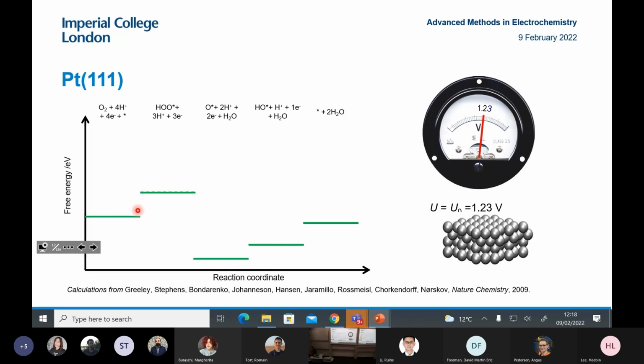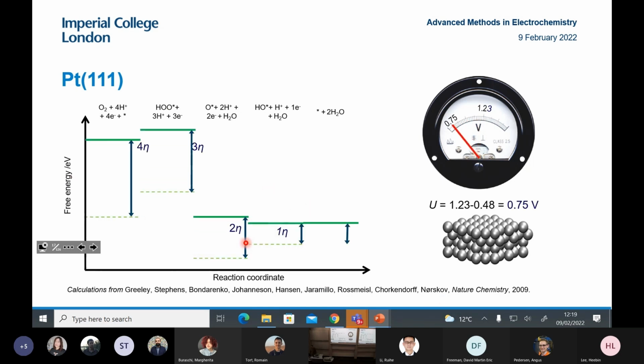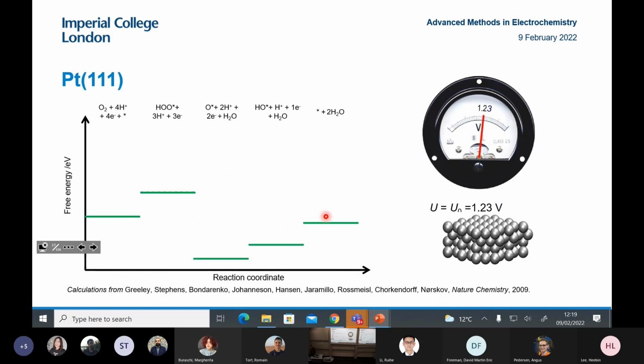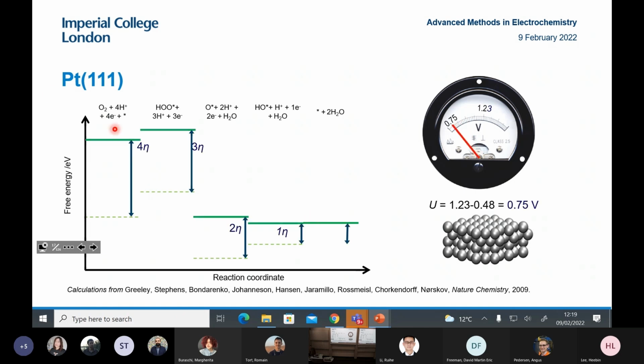So there's two steps in particular which are uphill. First going to OOH formation, and then this step is very downhill, and then this step here going from OH to water is very uphill as well. So actually it turns out this step is slightly bigger than this step. And to overcome this, you need to apply a bias equal in magnitude to this step. So it's about 0.5 electron volts, which is similar to the overall experimental overpotential. So it's only when the reaction is downhill that you have really, really high current densities.